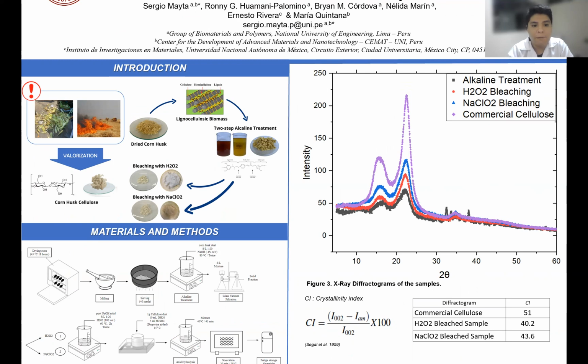Wide-angle X-ray diffraction analysis of extracted cellulose, commercial cellulose, and corn husk powder was performed using a Bruker D8 Advance X-ray diffractometer. The intense peaks in the diffractogram of the sample are located at values around 17, 22.7, 35, and 45. The appearance of sharp peaks is attributed to the typical crystalline nature of cellulose. The intensity of the peaks becomes sharper after chemical treatments, which indicates better defined crystalline domains of cellulose. Also, the peak at 17 corresponds to lattice plane 110, and the ones at 22.7 and 35 correspond to lattice planes 002 and 004, respectively.